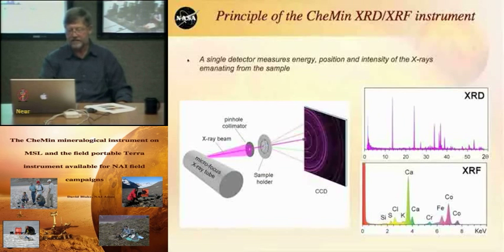And as they pass through the beam, two possible things can happen. Nothing can happen, of course, but one possible thing is diffraction, and the diffracted beams form these Debye rings on the CCD detector here. The second thing that can happen is that you can get X-ray fluorescence, and photons are emitted from the sample which have energies which tell you what elements are in the sample. And so this detector can collect both of those signals at once.